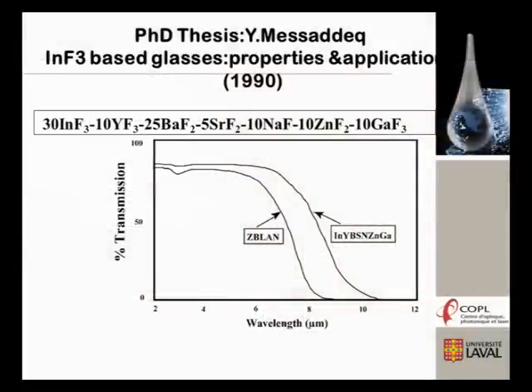And this is because of the process of preparation and also the technology. What we did at that time also, during my PhD thesis, we discovered a new kind of glasses based on indium fluoride, what we call fluoroindate glasses, because they have higher transparency than fluoride glasses. Fluoride glass, compared to silica, is transparent till 5 micron. Remember, silica is till 2 micron, which opens a large range of applications.